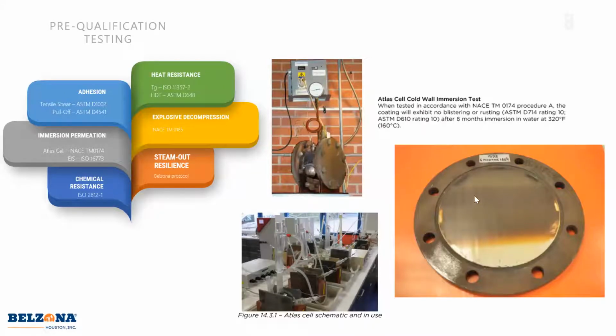Then they run this test for about 6 months at a certain temperature that they think the coating should handle, and they test it periodically for delamination, blistering, all types of defects. For it to be suitable for that temperature, it has to go the entire 6 months without any defects. As you can see here, there is a change in color, but there's no cracking, there's no blisters, there's no delamination. So that's a pass there.